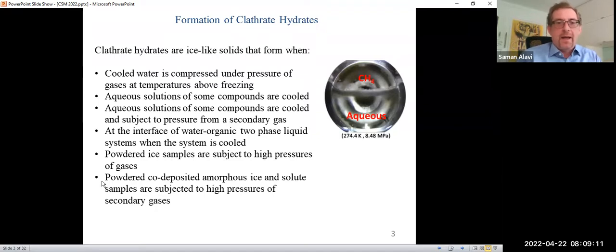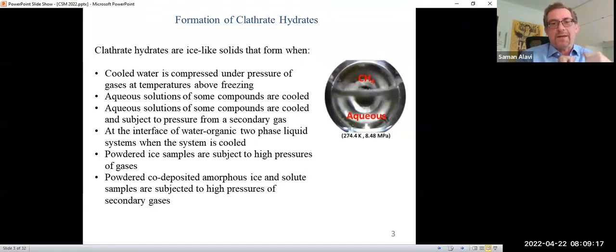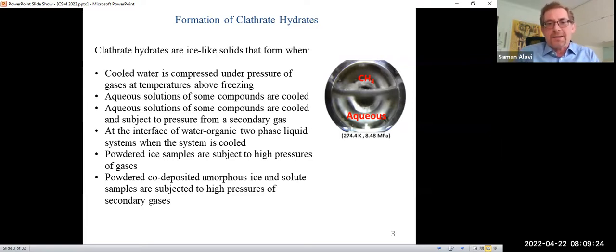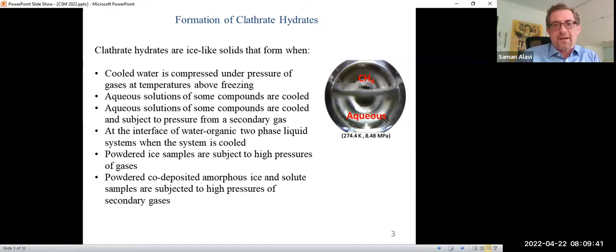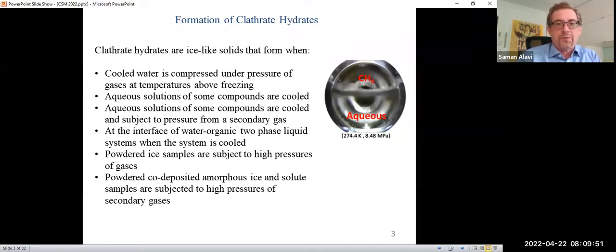There are also other methods where we can get powdered ice samples — we get an ice sample, powder it, and then subject it to high-pressure gas. That's another way of forming a hydrate. Or we can co-deposit gases — co-deposit amorphous ice and a solute. In our case, we do that with ammonia and methanol, powder the solid phase, and then subject it to high pressures of a secondary gas. Under those conditions, a hydrate can actually form from the solid amorphous ice phase. It's a little bit slower, but nonetheless the ice does transform to a clathrate hydrate.